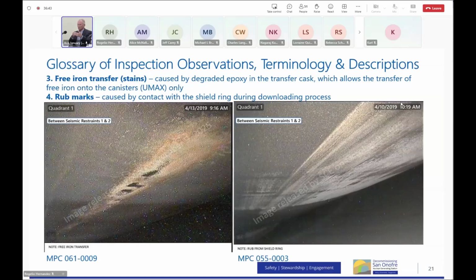And while it's sitting there for those 2 days, with this rust here and the canister there, ions in the water transport themselves across that 2-inch gap, and they affix themselves to the canister. So there's some iron, what we call free iron, that's been transferred from the cask to the canister through the water. Okay, it's on the surface. It's not a sign that the canister's rusting. It's iron particles on the surface that came from somewhere else. Okay, and that's called free iron transfer.